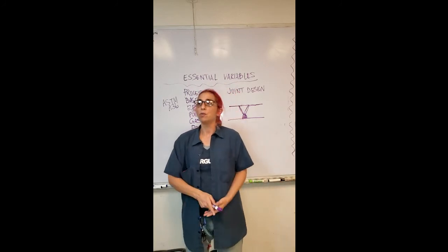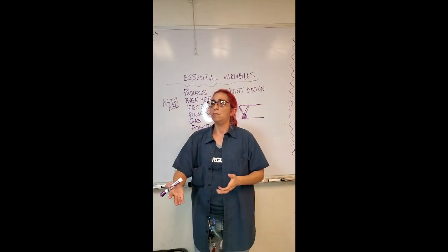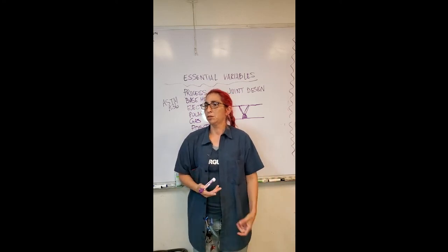GMAW-P is one of the only GMAW processes that is pre-qualified under AWS D1.1, because we're able to give it bursts of really hot arc. When we talk about short circuit, it's usually under 200 amps. So usually it's not enough to penetrate.